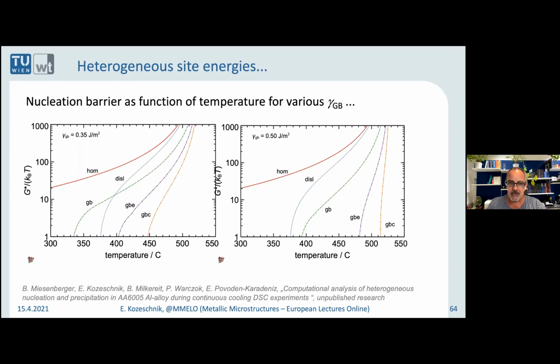Yeah, the analysis on the next is also interesting. So I was calculating the nucleation barrier as a function of temperature for different heterogeneous sites and for different values of the grain boundary energy. So this heterogeneous nucleation is apparently also a very strong function of these heterogeneous site energies. And when you go into literature and look for grain boundary energies for aluminum alloys, you will find values straight away between 0.3 and 0.6. And this diagram is simply showing you the consequence.